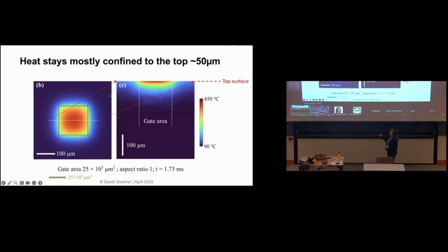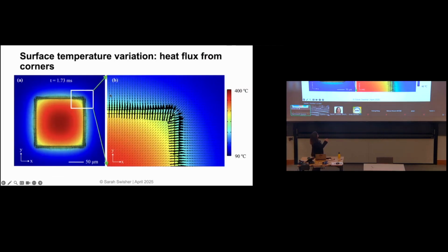So the larger this is, the farther you are, right, from the middle to the cool zone. And if you're farther away from that cooler zone, essentially you're going to be able to heat to a hotter temperature before the light turns off. And so we modeled that, and this picture is showing the flux, and what you can see is there's very little flux or heat flow here in the center because it's almost the same temperature. There's very little delta T, so you get very little flux. But right here at the boundary, each of these vectors is showing the direction and the magnitude of the heat flux. And so we can see that the magnitude of these vectors is huge right at this boundary where we get that big change from the gate to the substrate. And in particular, if you look at the edge versus the corner, notice how much more flux there is from the corner. So we can explain why this area and why the shape matters by looking at this simulation of the flux.